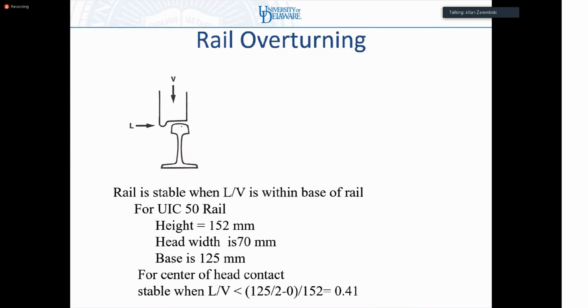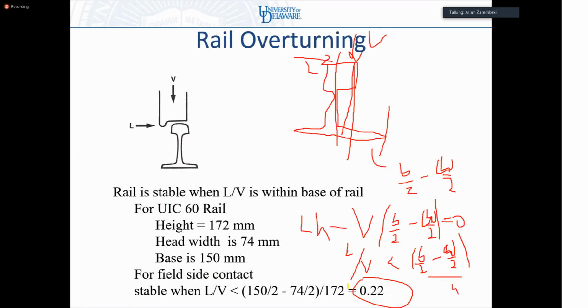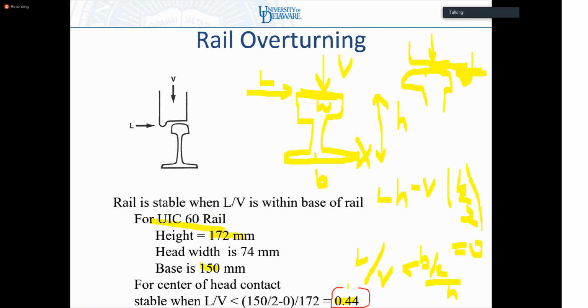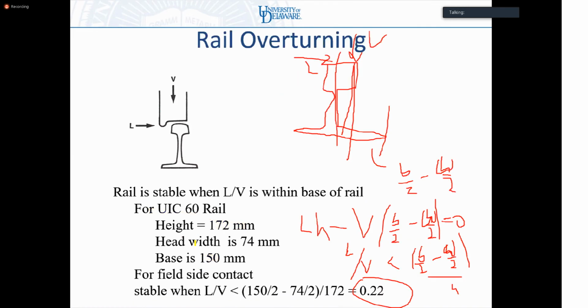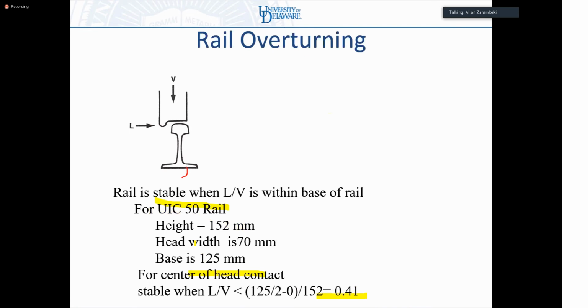For UIC 50 rail, for center head contact, let me go back to the yellow one. For UIC 50 rail for center head contact, it's 0.41 as opposed to 0.44 for UIC 60 rail. So this is where the higher height comes in, because the rail base is actually the higher height and the smaller base.